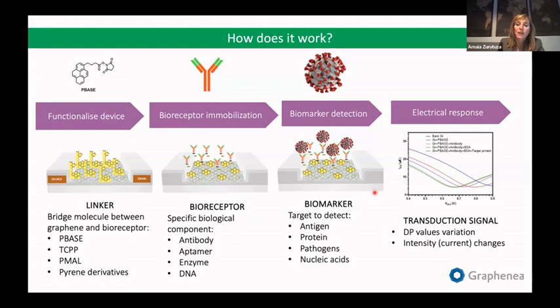The non-covalent functionalization typically has two steps. First, we put a linker on the graphene. I'm showing you an example here of PBASE because I will show some results on that later on. So we have pyrene-based molecules that are non-covalently interacting, by pi bonding, to the graphene lattice. That's why we call this non-covalent functionalization. And then the other part of the linker is the one that we attach covalently to the bioreceptor. And in this case, this is an antibody.